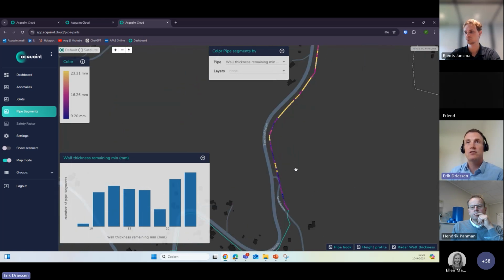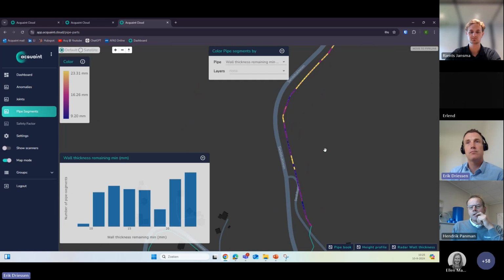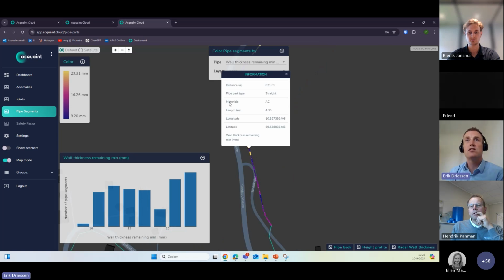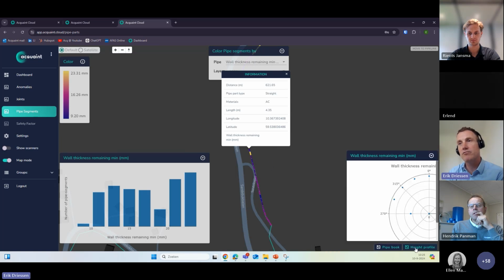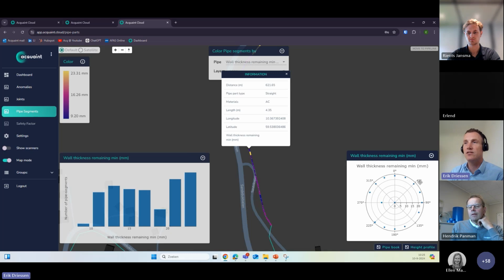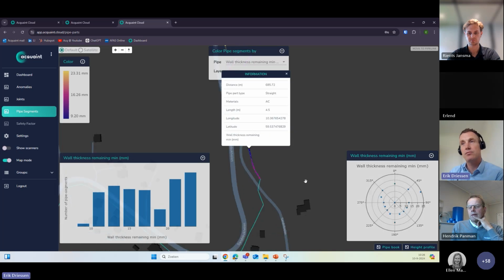So let's zoom into the last part of the pipeline with the smallest or the least healthy wall thickness. When we take, for example, one of the more blue ones, you can click on that pipe segment and then open the radar with the wall thickness. So here you see the wall thickness at the different clock positions in the pipeline. This is the y-axis, and the x-axis is basically the circumference of the pipeline. Here you can see that at the 9 o'clock position, for example, there's still 11 millimeters left of healthy wall thickness. When I select this pipe segment, for example, you get another view.